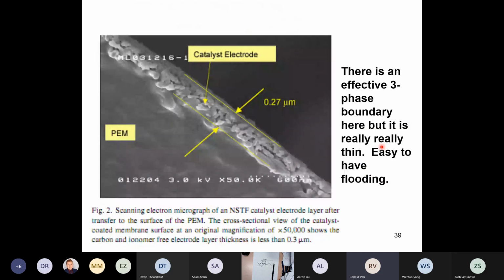So the reason why they didn't end up using it is the flooding problems and expensive processing. The processing really wasn't that expensive by comparison to the cost of the platinum and so forth. It was pretty easy. You could make this stuff on a roll-to-roll sputtering system, which 3M had. So you had a system where the polyimide support moved underneath a thermal evaporator to put on the whiskers, and then it moved into an area where it's heated to 150 to grow the whiskers, and then onto a take-up reel, all within a vacuum chamber. So it was very slick. But the flooding really became the problem. Operating this stuff without flooding is incredibly difficult.